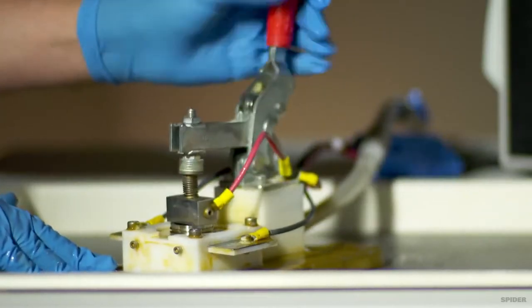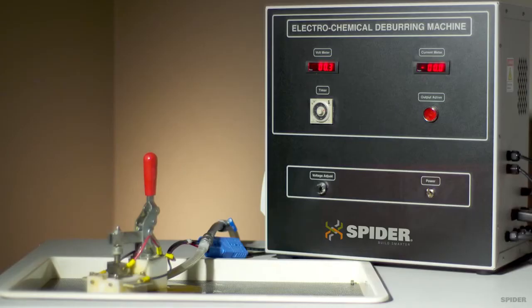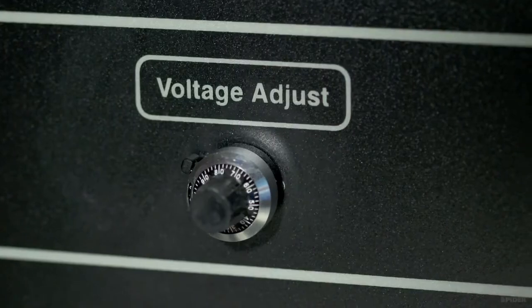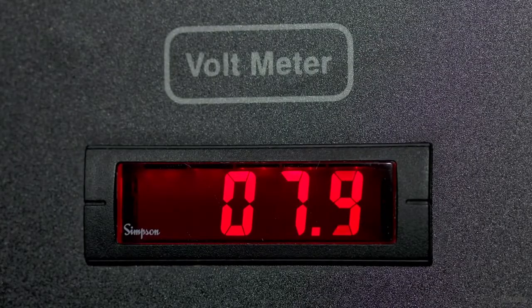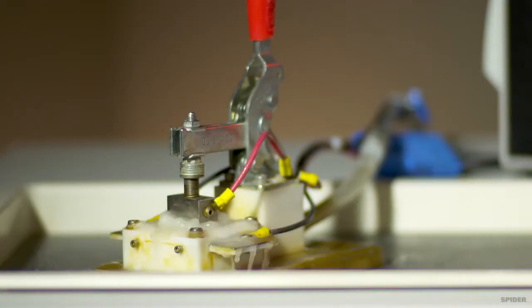Simply clamp it down which makes the electrical connection with the part, activate the Spider ECD with the foot switch, and notice the flowing electrolyte. Using the voltage adjust knob, the voltage is regulated up until about 10 amps of current flow, and you see the fluid is bubbling.